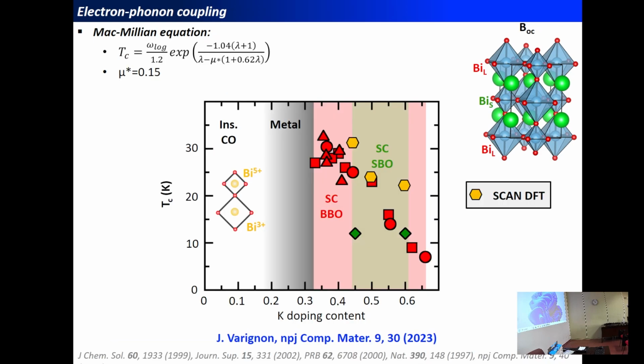And finally, we can compute the critical temperature, using the modified McMillan equations in which the lambda is entering this expression, and we need the logarithmic average frequency of the system. And so for this frequency, we took the value of the literature. And so if we do that and report on the experimental phase diagram for these bismuthates, we see that our DFT calculations are well reproducing the trend observed experimentally for the bismuthates with a decreasing critical temperature when we increase the doping content in the material.